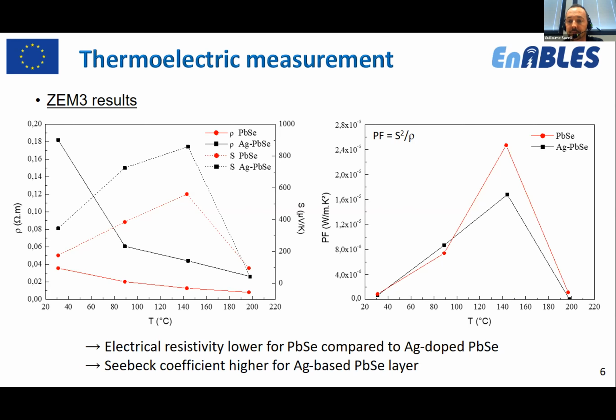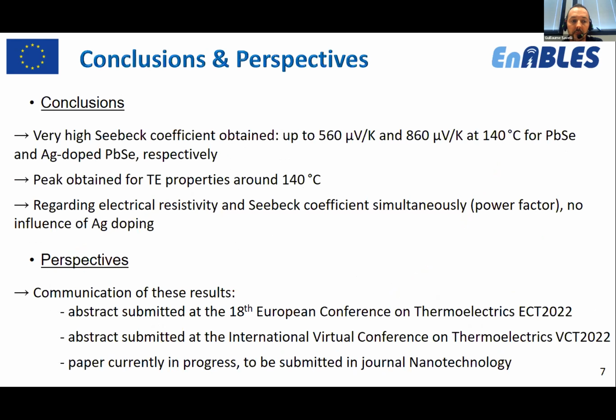on the power factor. So in this case, we obtain a very high Seebeck coefficient, up to 560 microvolt per Kelvin and 860 microvolt per Kelvin at 140 degrees C for PbSe and silver doped PbSe respectively. A peak was obtained for the thermoelectric properties around 140 degrees C. And also regarding the power factor, we don't see any influence of silver doping.